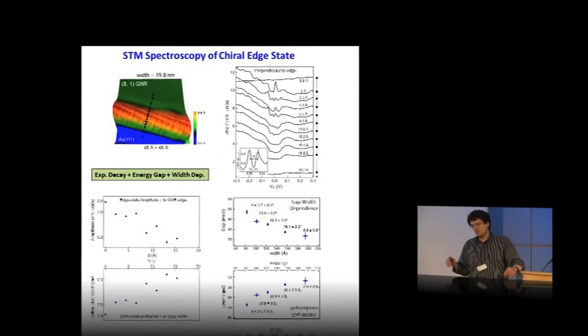Let me make two comments on that. First, I want to point out that people have grown graphene on gold 111, and they see that the gold 111 does not interfere too much with the electronic structure of the graphene. It still has the Dirac cone, and there's not a lot of charge transfer for that perfect system. However, here we have an imperfect system because we have these nanoribbons, and it is not a perfectly clean system. There is also adsorbates down there.